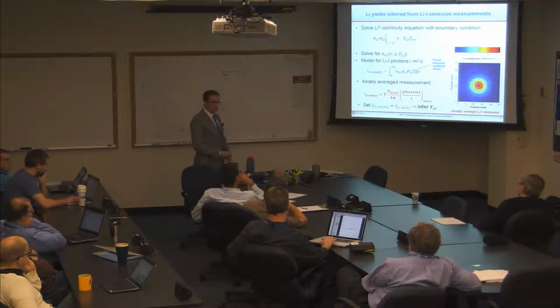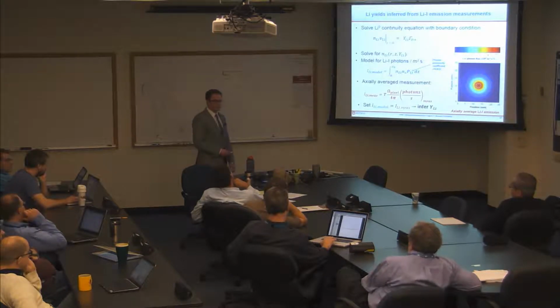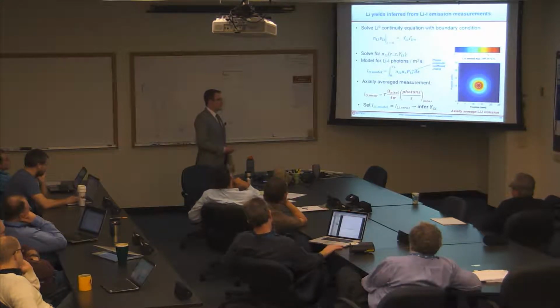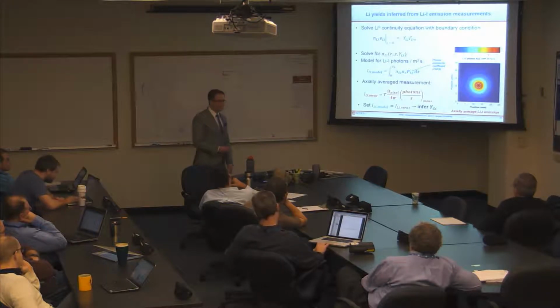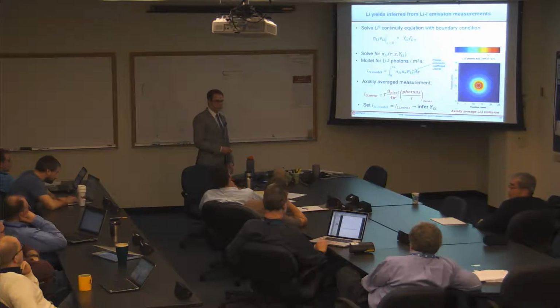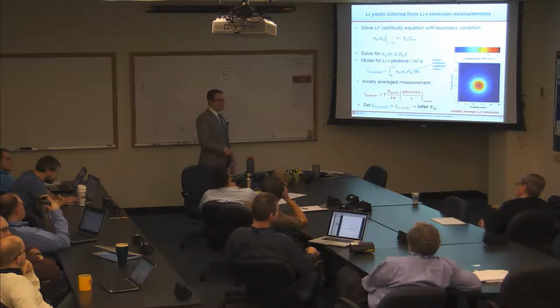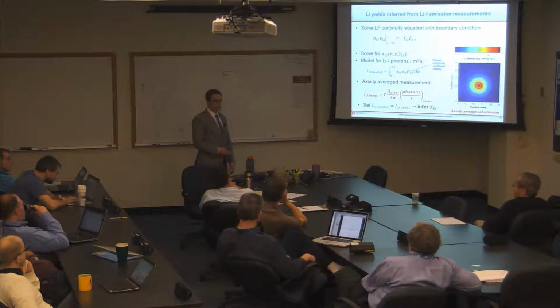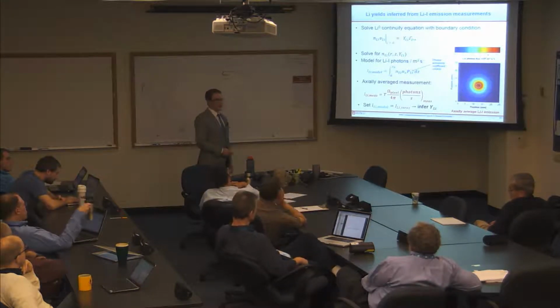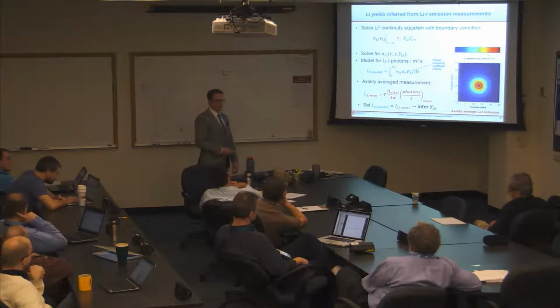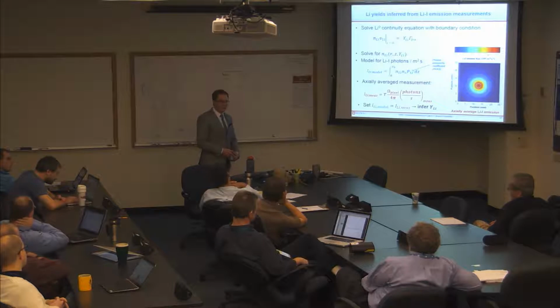How do you get V lithium? V lithium, I assume, is equal to 1 eV, or the energy is 1 eV. Just flat out independent of everything else. Yeah. I did some scans in what velocity you assume. It turns out not to really matter that much because the ionization mean free path is so short that it's just ionizing so close to the target that it doesn't make that much of a difference. So I didn't use a full Thompson distribution like you might expect for sputtered atoms, or a thermal distribution for evaporated atoms. But the results were very insensitive to what velocity you use.